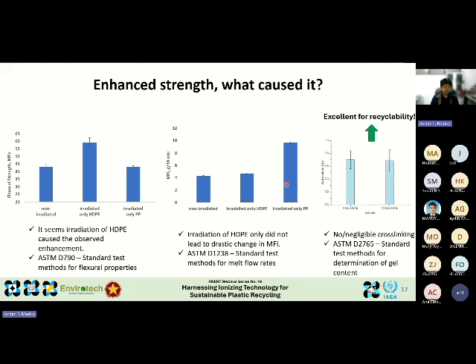And we know that, in fact, polypropylene, when irradiated in air, tends to degrade. That's why its melt flow index increases with irradiation. However, for high density polyethylene, there is not a significant increase in the melt flow index with irradiation. This is very important because during processing and manufacturing, the melt flow index is a very important parameter to determine the throughput of the manufacturing process.